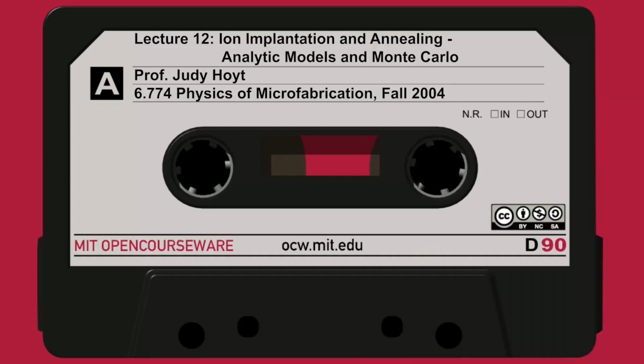So where D is the diffusivity of boron in silicon at that temperature, and we can look that up in the charts. It's about 10 to the minus 12th centimeters squared per second at that concentration and temperature. So in 1 second, you've already put into the wafer 10 to the 14th atoms per square centimeter, a very high dose. So if I want an implant of 10 to the 12th, there's just no way you can get that low of a dose with any kind of control by using a chemical pre-dep technique. So again, this was the big breakthrough in ion implantation.